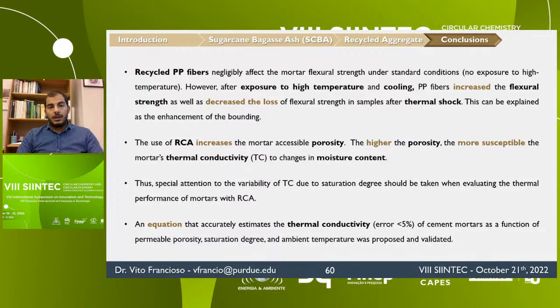And also an equation that accurately estimates the thermal conductivity of cement mortar with an error less than 5%, as a function of the permeable porosity, saturation degree, and ambient temperature, was proposed and validated in one of our studies.